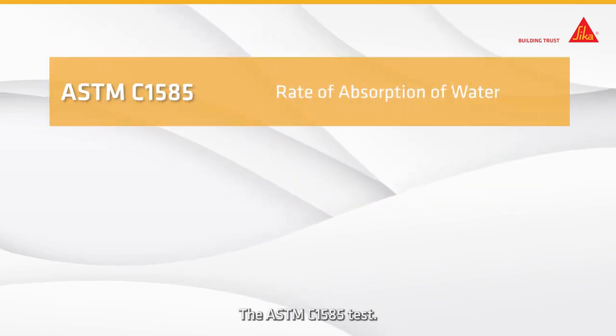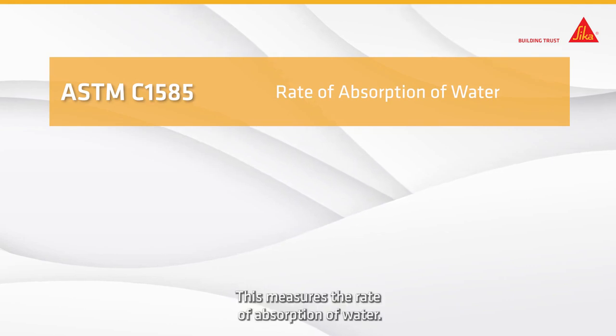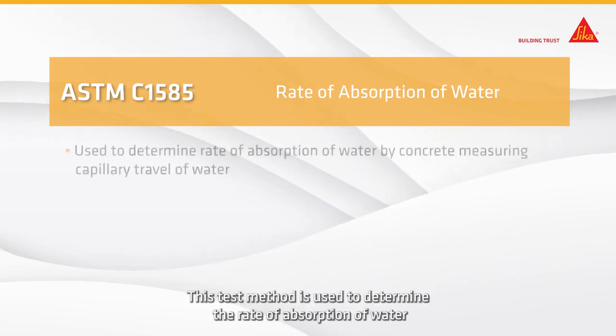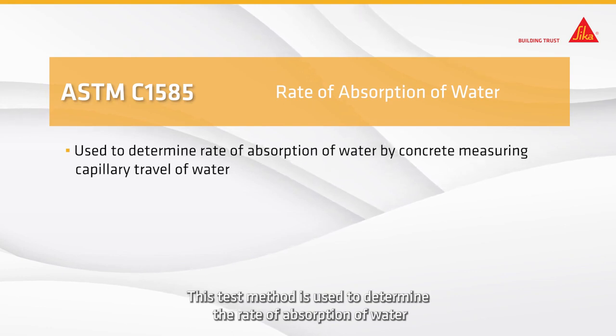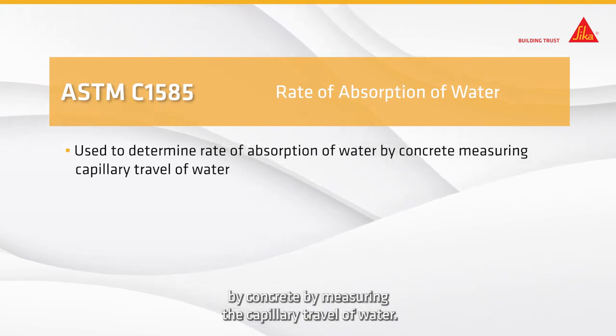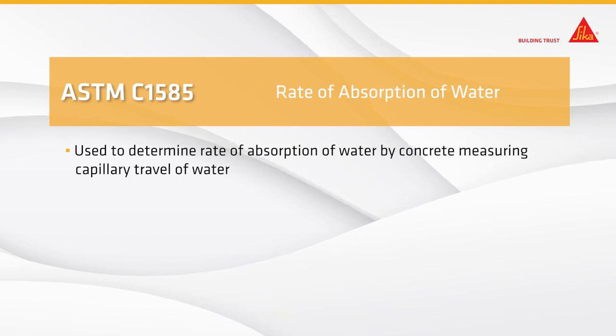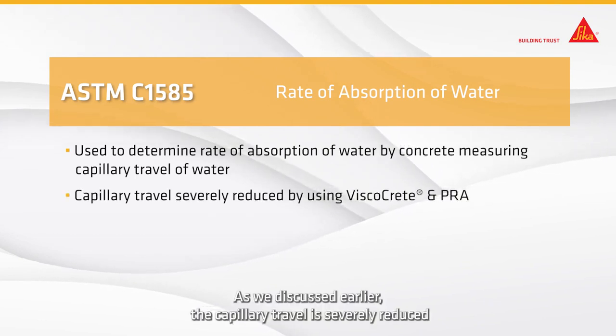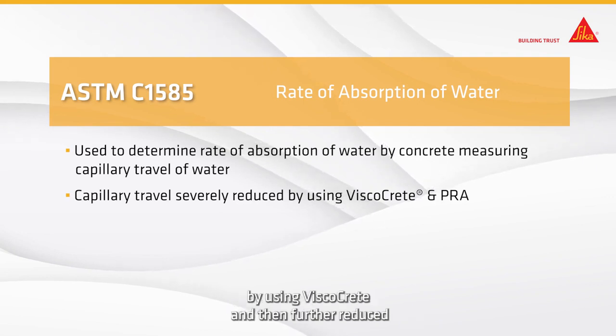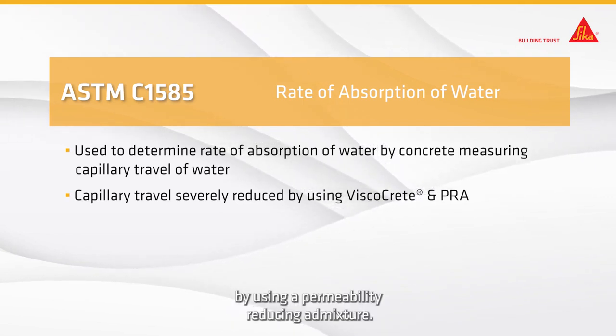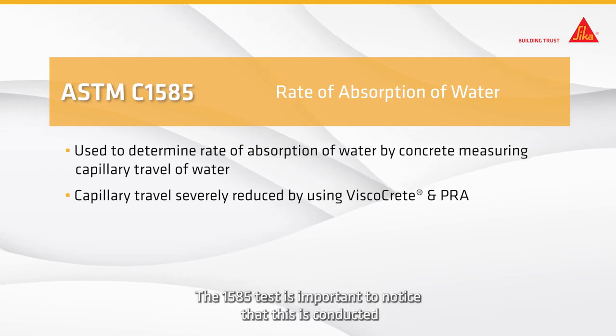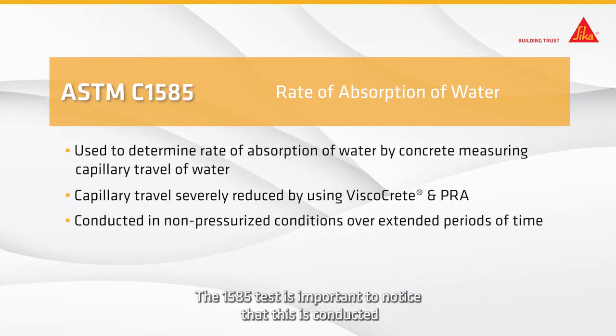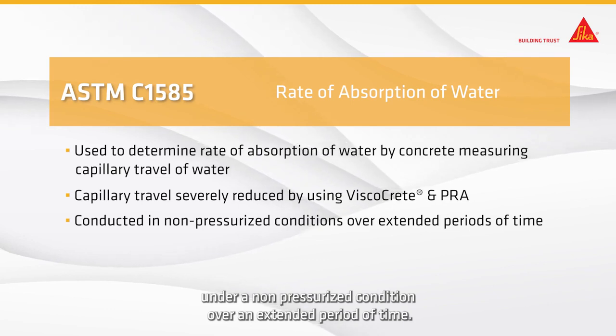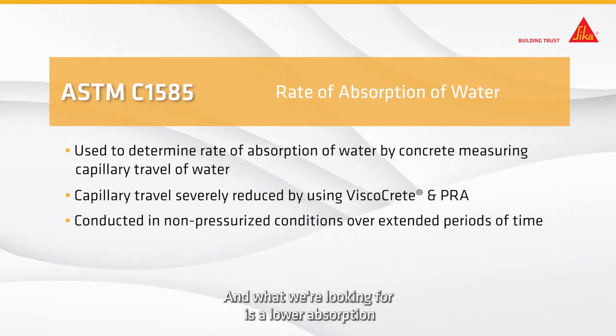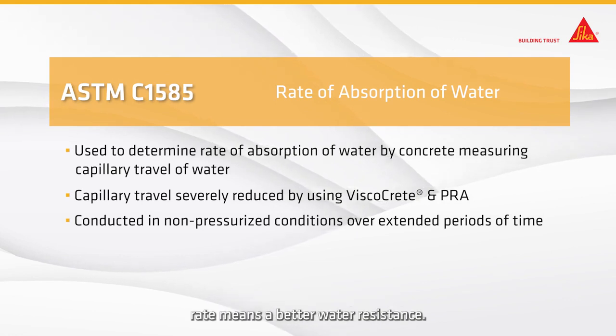The ASTM C1585 test. This measures the rate of absorption of water. This test method is used to determine the rate of absorption of water by concrete by measuring the capillary travel of water. As we discussed earlier, the capillary travel is severely reduced by using Viscocrete and then further reduced by using a permeability reducing admixture. The 1585 test is important to notice that this is conducted under a non-pressurized condition over an extended period of time. And what we're looking for is a lower absorption rate means a better water resistance.